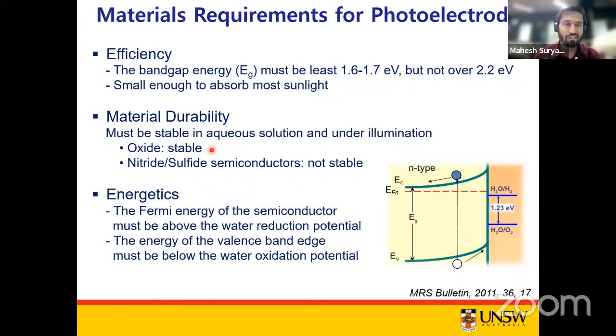And of course, at the last, these materials should fulfill all these requirements simultaneously. That means a material with a suitable band gap, let's say about 1.6 to 1.7, or around 2 electron volt, is considered an ideal material, but it will not be useful if it is not stable in the water electrolyzer. For example, here I have mentioned the oxides are stable, but the problem with oxides is they are usually very wide band gap semiconductors, whereas nitride and sulfide semiconductors are usually narrow band gap. Of course, not all, but most of them are narrow band gap semiconductors. But the problem with these nitride or sulfide semiconductors, and also the phosphates, is they are not stable in the electrolyte.